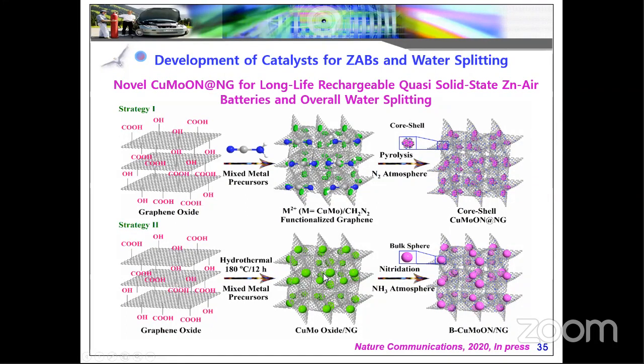Another thing, when we go for the ammonia methods, first we need to develop metal oxide, and then the metal oxide should be converted into metal nitride using ammonia. When converting metal oxide to metal nitride, the metal oxide is not fully converted because the metal particles are big. The outside surface may be easily converted into metal nitride, but the inside is not converted.